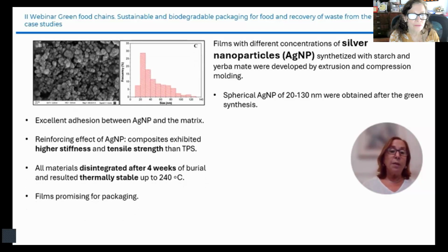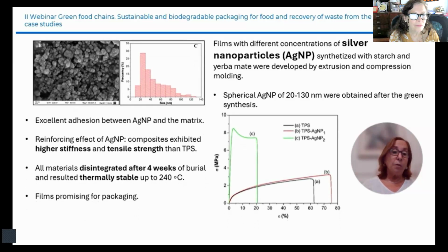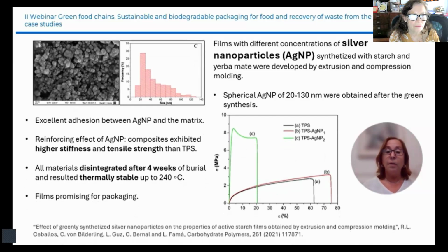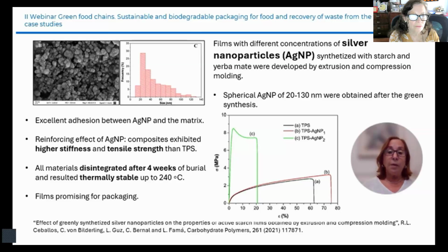They also promoted a very important reinforcing effect because the nanocomposites exhibited higher stiffness and tensile strengths than thermoplastic starch, as you can clearly see in the stress-strain curves. The green curve is related to the nanocomposites. All materials disintegrated after 4 weeks of burial and were thermally stable up to 240 degrees centigrade. So these new films were also promising for packaging.